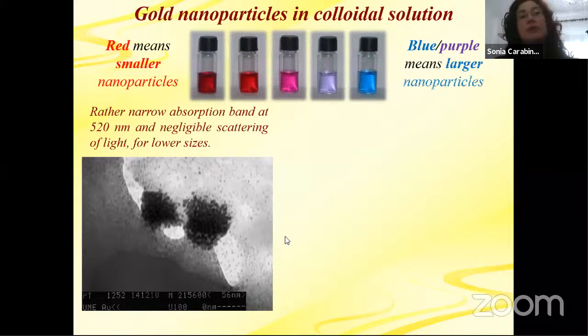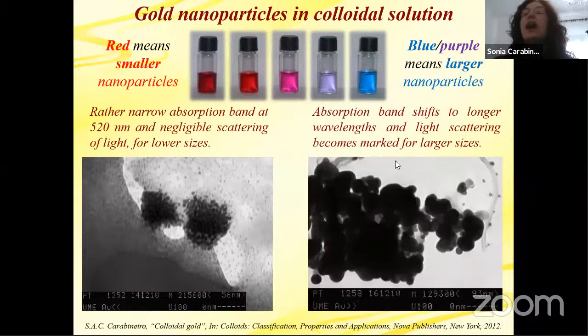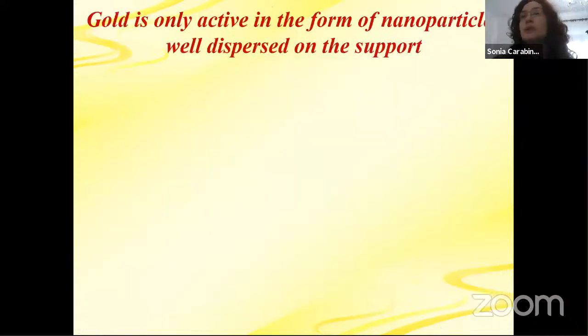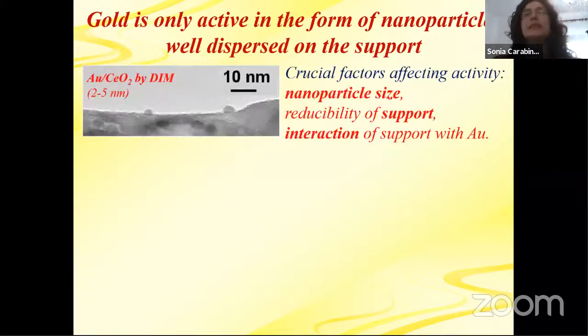So we have here a TEM image of small nanoparticles and another TEM image of larger nanoparticles. And we know that gold is only active in the form of nanoparticles well dispersed on the support, because, as I said before, gold is inert in the bulk state. And that's the reason why for so long it was not known that gold could be a good catalyst, because it was inert in the bulk state. So crucial factors affecting the activity of gold are the nanoparticle size, which is very important. The smaller, the better, usually. The reducibility of the support, and also the interaction of the support with gold.